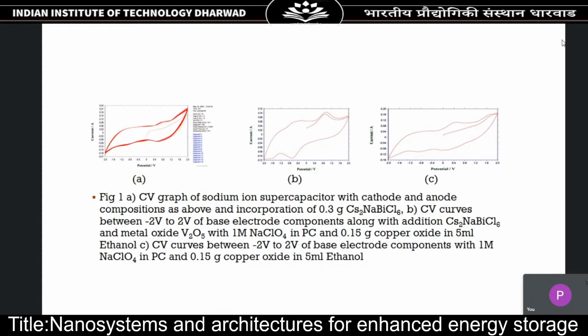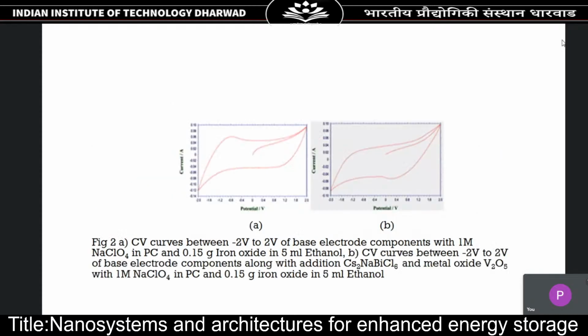You can see that the area under the curve is increased when we add the nanofluid into the electrolyte. And this graph shows when we add iron oxide into the nanofluid. Again, the area under the curve is considerably increased when compared to the base electrolyte.